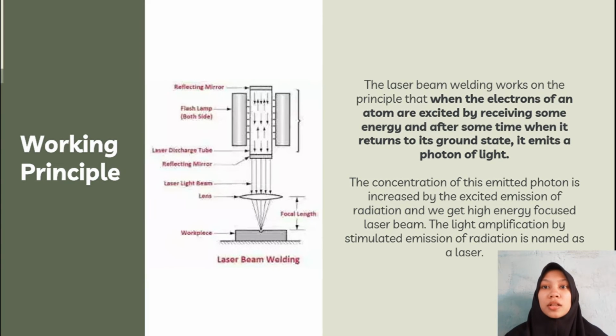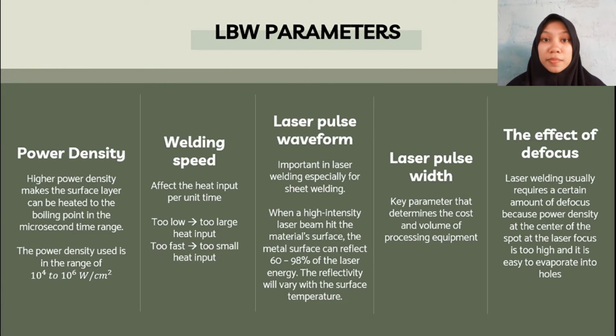There are several parameters in performing laser beam welding, such as power density, welding speed, laser pulse waveform, laser pulse width, and the effect of defocus. The most important are the first two parameters. High power density means the surface layer can be heated to the boiling point in the microsecond time range. So when we have higher power density, we have a shorter time range. The power density commonly used in the LBW process is in the range between 10 to the power of 4 to 10 to the power of 6 watt per centimeter squared.